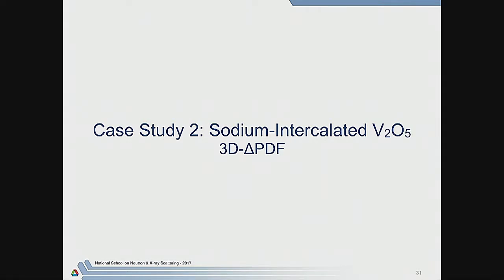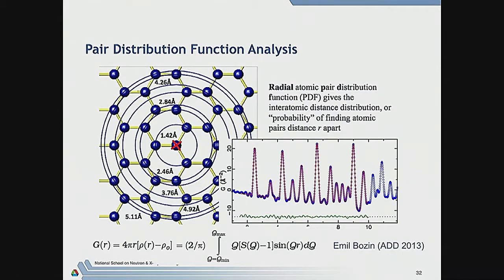Okay, so you've had electron PDF, is that right? Techniques. So, and as you know, it's very powerful and it's also an extremely popular way of measuring disorder, where basically instead of doing a Rietveld refinement to some powder diffraction data or even amorphous data, you do a Fourier transform of the total data set. And from that, you determine the probability of all of the interatomic vectors in the material, okay, as a function of increasing R, those vectors that represent vectors in the average structure and those vectors that represent deviations from the average structure. Okay, that's what you learned, was it? Okay. So it's a very powerful technique.